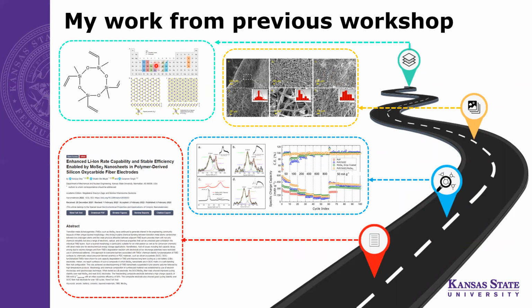They were used as a reinforcement material, and the matrix for the composite material that I used was a polymeric precursor named 4-TTCS. To be specific, it is 1,3,5,7 tetramethyl 1,3,5,7 tetravinyl cyclotetrasiloxane. These materials were mixed with polyvinyl pyrrolidone to obtain a viscous and homogeneous solution for electrospinning to obtain fibermats, which were then cross-linked and pyrolyzed at certain temperature to obtain the final product.